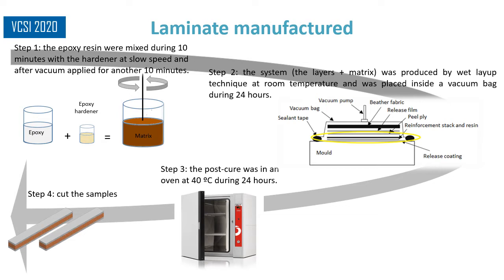During the first 4 hours, the bag remained attached to a vacuum pump to eliminate any air bubbles existing in the composite. Step 3. The procedure was followed according to the manufacturer's datasheet: epoxy resin in an oven at 40 degrees during 24 more hours. Finally, cut the samples to the appropriate dimensions to test.